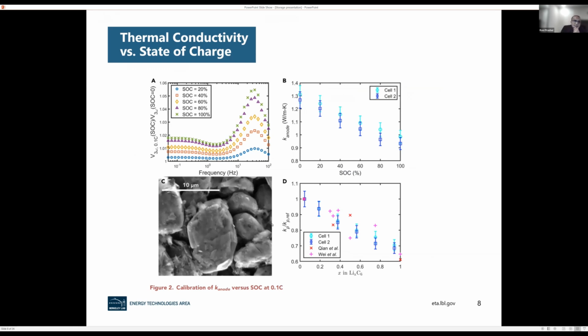So this is state of charge. 0 means pure graphite, okay, no lithium has gone inside. And then 0.1 C means we are charging it very, very slowly. And 3 omega is the signal from the sensor, right? State of charge 20% means that 20% of the battery is charged. State of charge 100% means 100% of the battery is charged now, right? And you can see that the signal is changing dramatically, right?